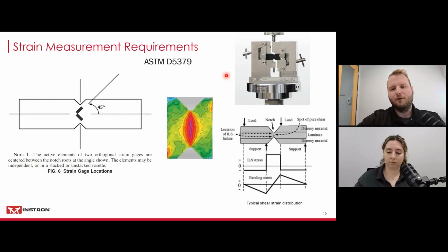One example for that, the biaxial strain measurement, which is the relation between the axial and the transverse strain, is often required in composite testing standards to determine the Poisson's ratio, like we covered before, and also the shear strains of your material. So a good example for that is a V-notch shear test, as it is described in the ASTM D5379 testing standard. That's a good example for a standard that requires you the determination of the shear properties of your material.